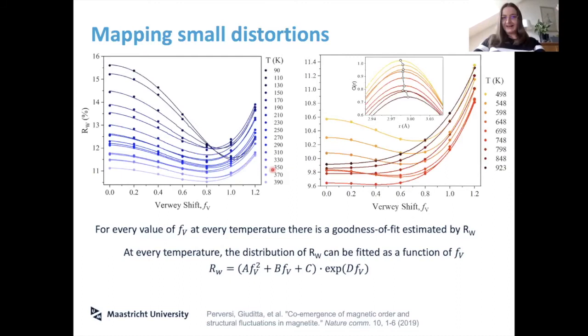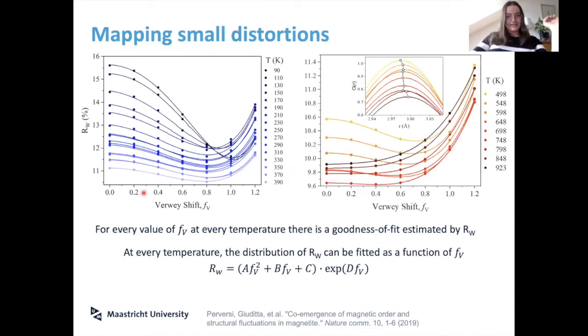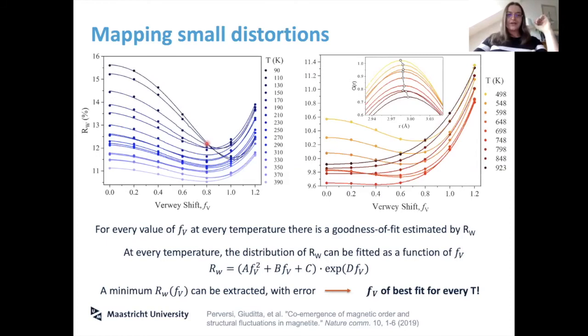For every one of these models you fit the data, and at the end you have a distribution you could fit with a mixed polynomial-exponential function. Then you start seeing a trend. Since you get your minimum, you can also derive which distortion fraction is the best fit for every temperature. For the two lowest temperatures, there's no doubt: 100% distorted monoclinic is the best fit. But above the Verwey temperature you start seeing something very interesting.